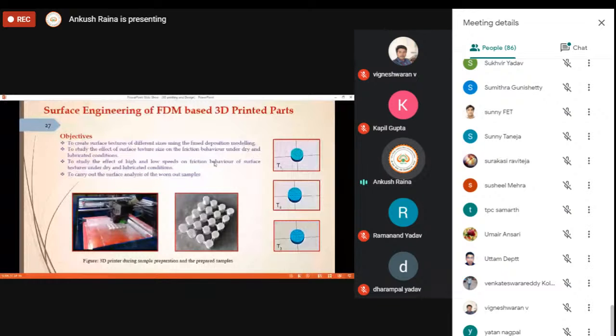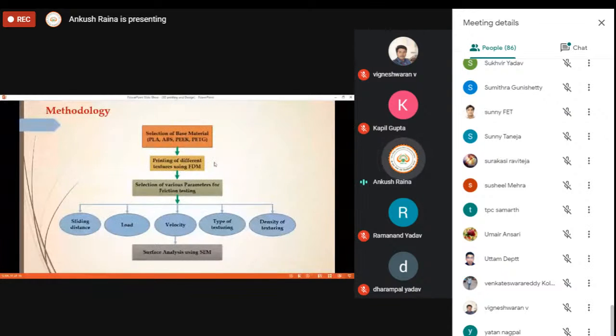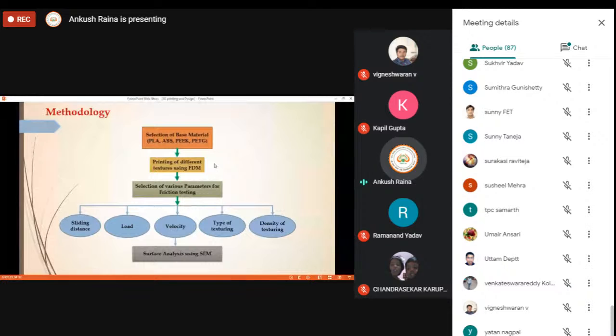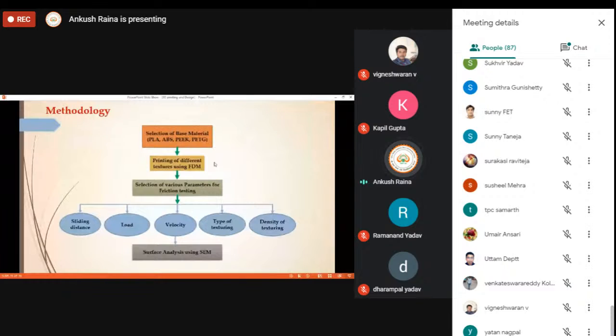So what was the process? Here we have used PLA, not the other materials. So we selected the base material, then printed, then various frictional parameters were selected. The sliding distance is an important parameter, load, velocity, type of texturing is also an important parameter, and density of your texturing, how dense the textures are, that is also an important parameter. So based upon all these five parameters, we carried out the testing, and then the surfaces were analyzed.